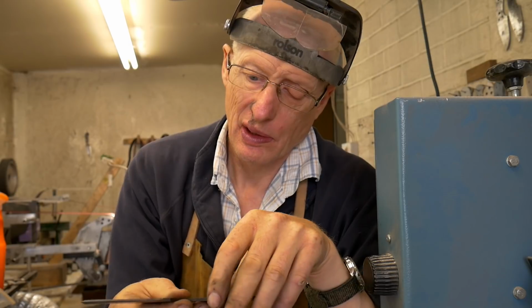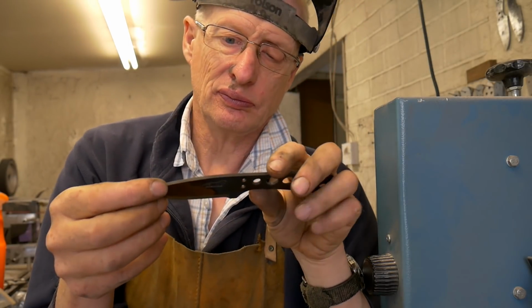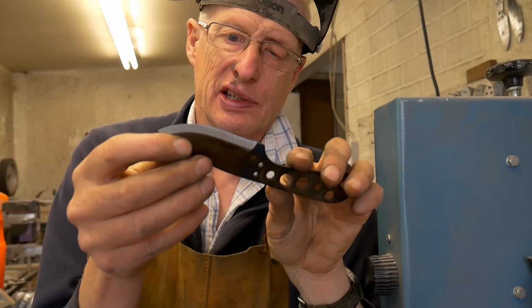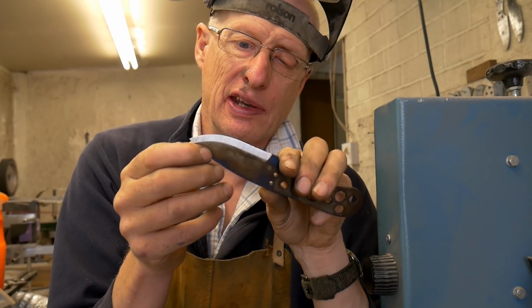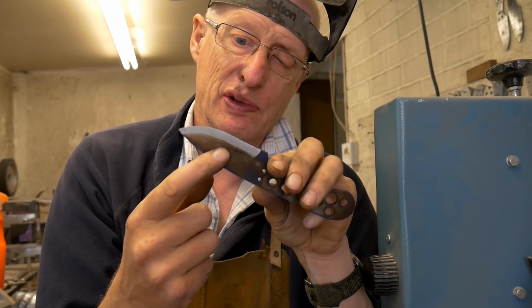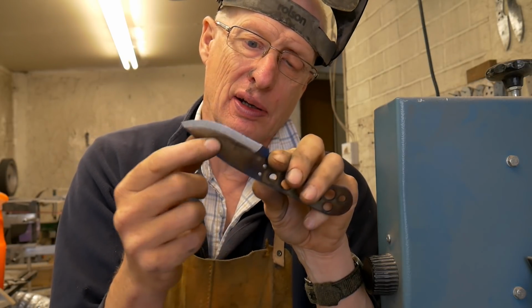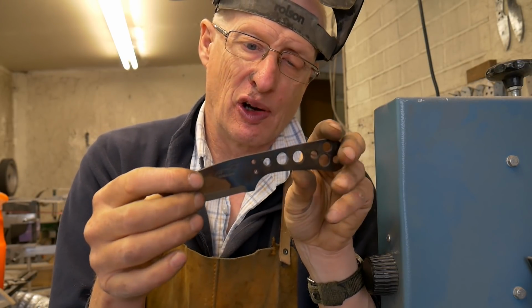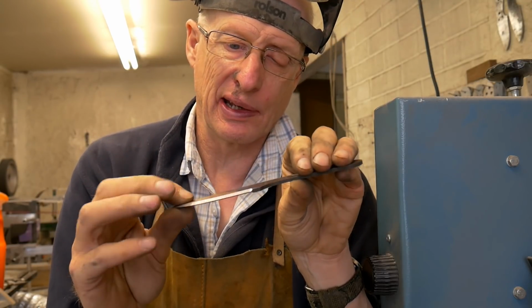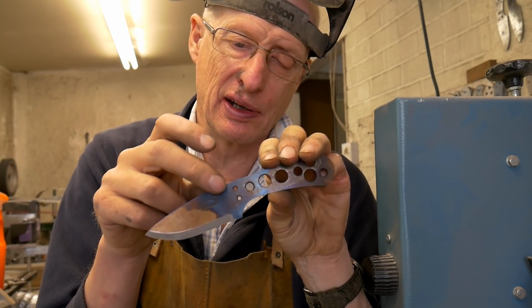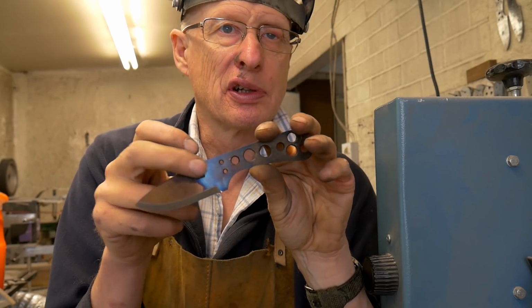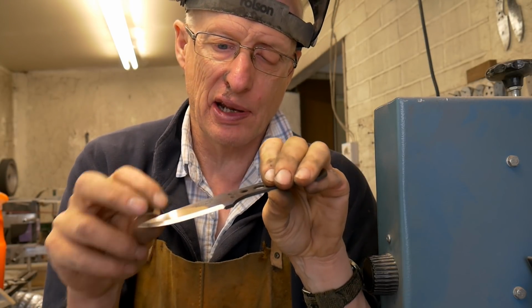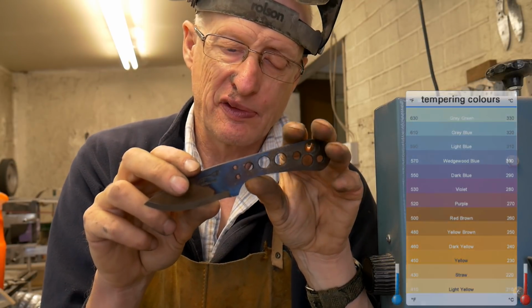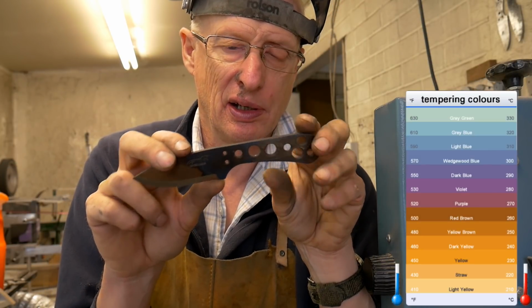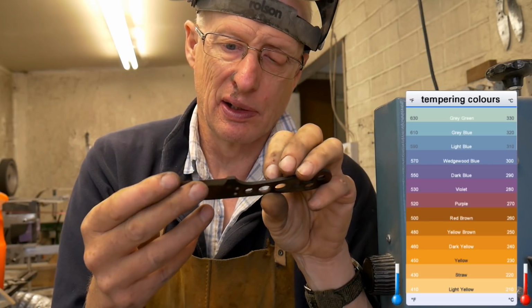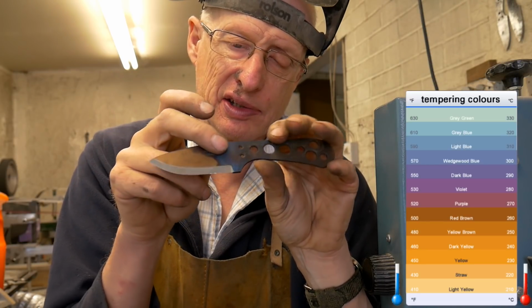The heat treat colours: you can see the true colour of the heat treat is this sort of a dark golden browny colour, but you get a mixture of different colours on the blade, and then for example there's a bluey colour here. Now if anyone is used to oxidation colour charts, you'll realise that the blue colour indicates a very high temperature, over and above 300 degrees centigrade. But in this case, this colour doesn't indicate that at all.